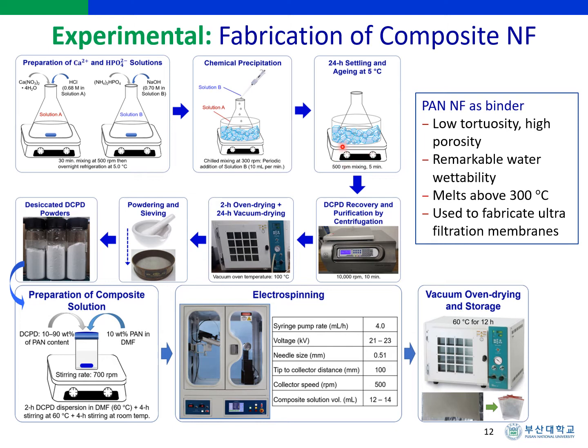The aged DCPD precipitates were then separated from the supernatant and rinsed twice with deionized water through a Combi 514R centrifuge, operated at 10,000 rpm for 10 minutes.